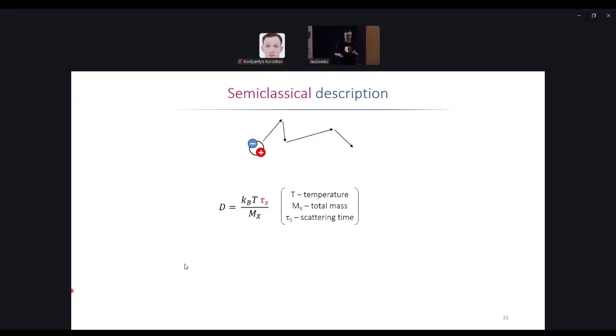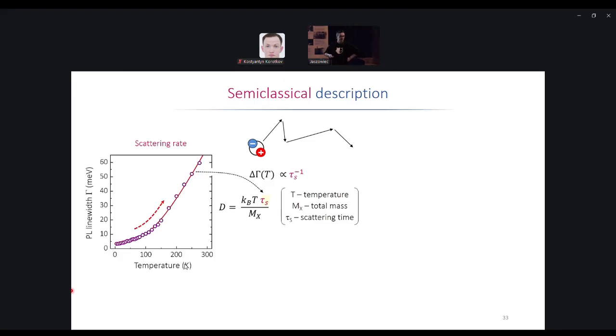And not just be sad because you don't have a 2D Fourier spectroscopy experiment. What can you do? Measure the line widths, exactly. With line widths, again, one needs to be careful because the line width is a combination of many factors. But if the line width goes down to a very small value at low temperature, then you can use the temperature-dependent line width as a proxy for the scattering rate.